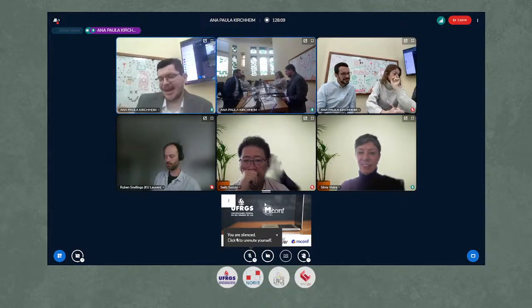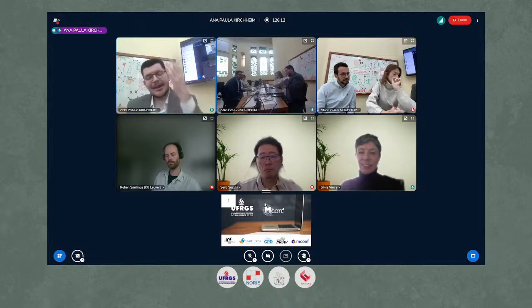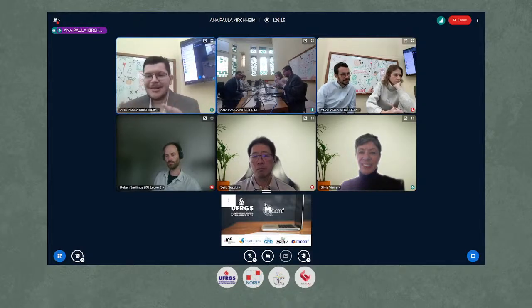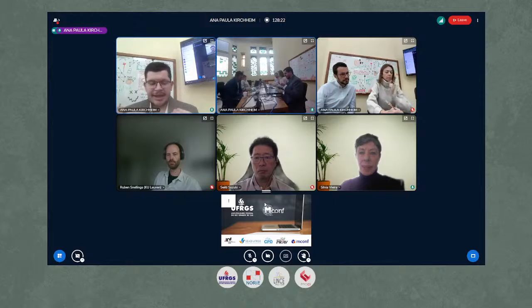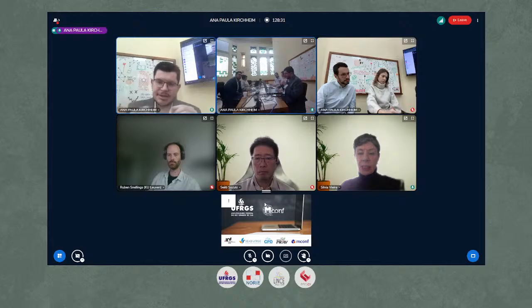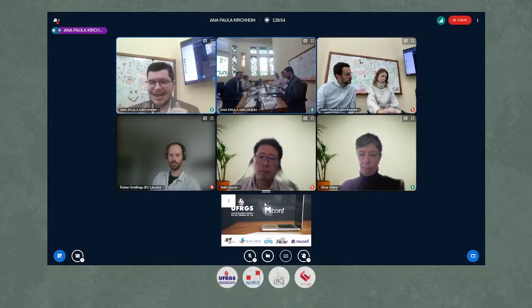I was talking with a person from the industry, because we have this problem as academics, we don't know how the industry operates. So what they said to me is, when you add calcium fluoride as a mineralizer, you adjust the kiln to have the mineralizer. So you adjust the kiln rotation time, you adjust the flame length, and this kind of thing. While phosphorus maybe is coming from the raw mill. So I believe the effects on alite crystal size, as you say, I saw correlations and I was, oh, very nice, and put it in.